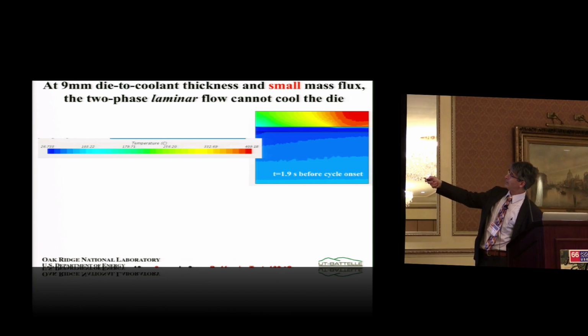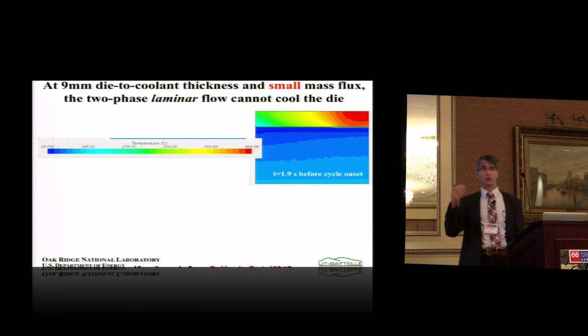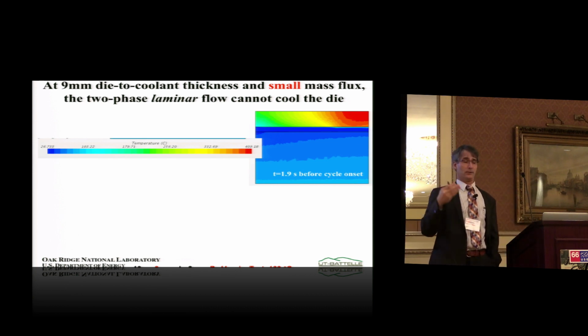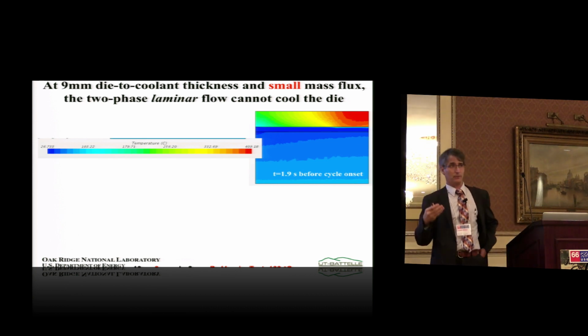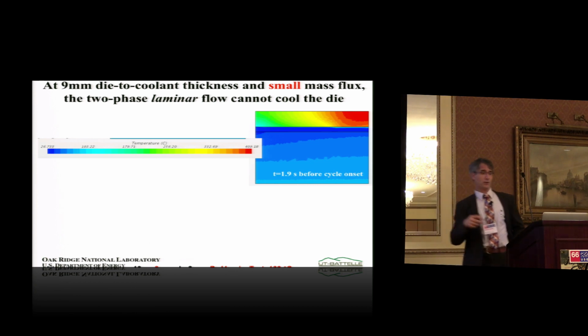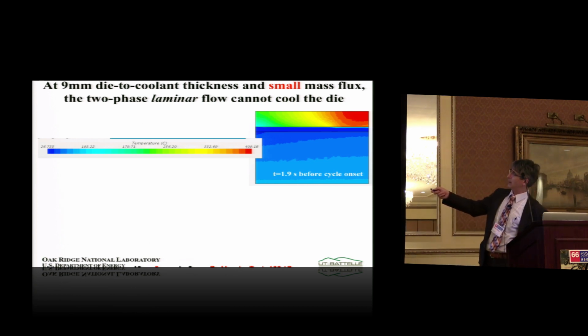For a 9 millimeter thickness, that's a die right here on top of the cooling channel. The molten metal will be up on the top surface, and the molten metal is not simulated. Instead, we impose that heat flux that I showed on the first page. So we remove that heat flux, and we're trying to see basically what flow rate do we need for the coolant to keep the die temperature under some acceptable numbers. So you see, this is before cycle onset. We simulate a couple of cycles in order to make sure that we reach steady state.